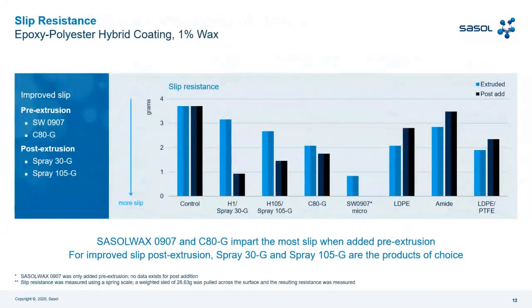Here are the first results. You can see slip resistance. The control has a very high value, so for performance you need to look for the lower value. In pre-extrusion, Sasol wax 0907, the microcrystalline wax, achieved the best result of all Sasol waxes, and also with respect to the other waxes that we tested. Then follows C80G in pre-extrusion, the micronized with melting point 80. For post-extrusion, post-added, you can see Spray 30G has the best results.